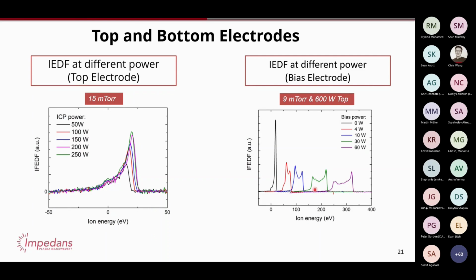And maybe a bit hard to see here, but in general, the area under these curves stays the same. So as you increase this power, you have pretty much the same ion flux, you just have higher energies. Therefore, in an ICP tool, you can independently control the energies by changing the bias power, and you can change the ion flux, which is basically like etch rate and so on, by controlling the top power.